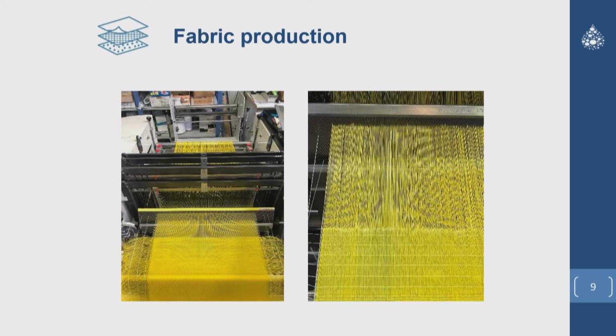But here we had two main problems. The first thing is this is quite a difficult filament to work with to produce the fabrics. It was a bit too hard to work with them, so we need to optimize it so that it's more smooth to use during weaving. And the second thing is we made 3 different fabrics, so a twill 2-2, a twill 4-4, and a unidirectional one. And with the twill 4-4, we saw that during the first lab trials to make a composite, we had some shrinkage of the material.